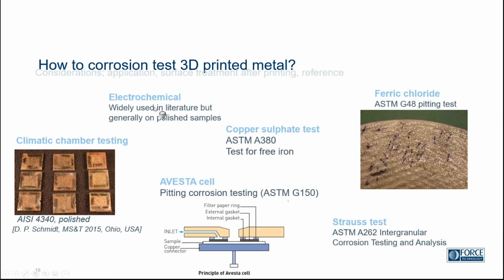If we take something like the electrochemical tests, it gives good quantitative data, but it's hard to do on something as printed, because the surface texture has an extremely large influence on the results you're getting, and therefore also something like the specific pitting corrosion test with the electrochemical cell is difficult. But then you can use something like a G48 pitting test or one of the other immersion tests, or you can use climatic chambers like a humidity chamber or neutral salt spray testing, which is commonly used both in the verification of normal stainless steel and for various offshore purposes.